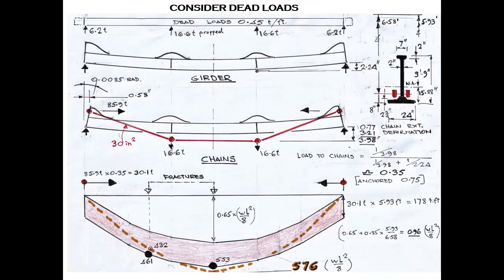So that induces a circular curve, downward bending into the girders, which of course is additive to the effect at the top. It means that in theory the chains carry 35% of the load. The cast iron carries 65, which sounds okay, except remember that the bending moment applied by the chains induces a further sagging moment, which is the coloured bit at the bottom of the diagram of the bending moment there. The total bending moment, from the 65% of the load carried by the cast iron, gives a certain figure. You must add on this bending effect due to the pulling in of the chains. So you end up with a total bending moment of 553, whereas if the cast iron did the whole job by itself, you'd get 576. So the only benefit of the chains is about 4%. It's not really worth having, is it?